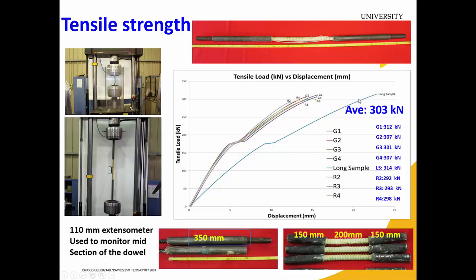You can see here that there is another set of data which is a bit away from the rest, because most of the data are close to each other. The reason is that another test was carried out with an exposed length higher than 200 millimeter. The intention was to see how the exposed length of the sample affects the tensile strength. It was observed that the peak value is almost the same, around 30 ton. However, the stiffness decreases with an increase in the exposed length of the sample.